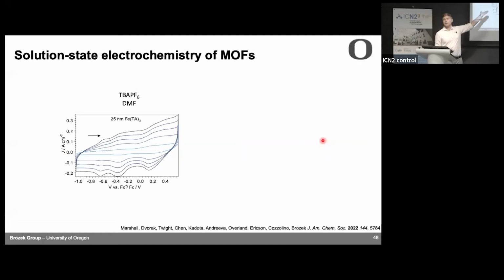So it turns out we can run solution phase electrochemistry. To the best of our knowledge, this hasn't really been done before, where you take a colloid of a MOF and just run a normal CV. And so we saw these CV traces that almost look like molecules, molecular electrochemistry, multiple fairly reversible redox waves. But what's weird is that this MOF, for all intents and purposes, really just has one type of iron site. And yet we're seeing redox waves that differ from each other by hundreds of millivolts.